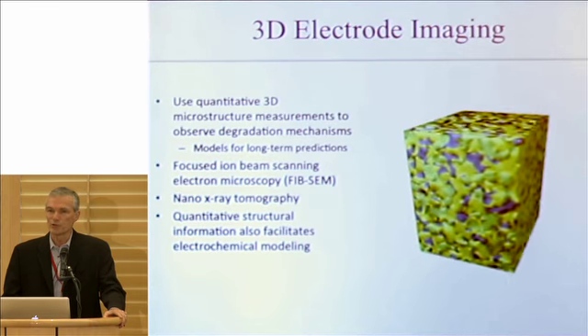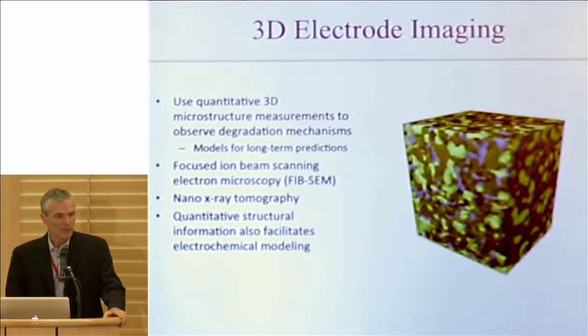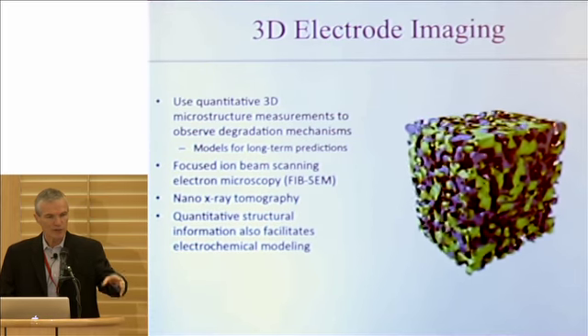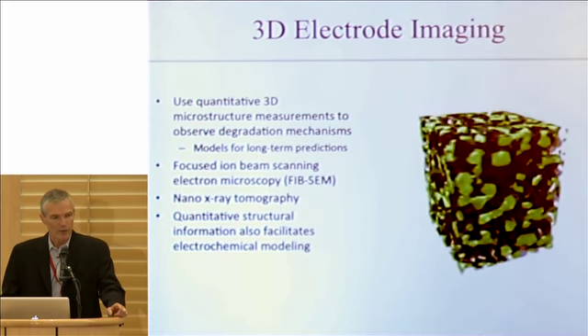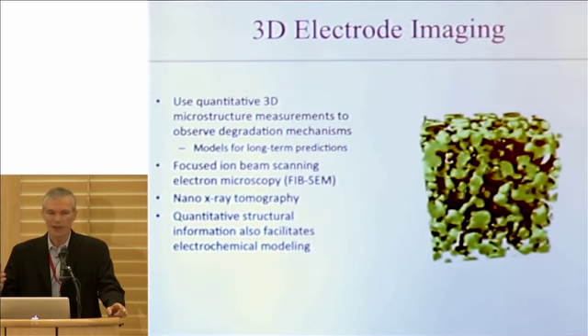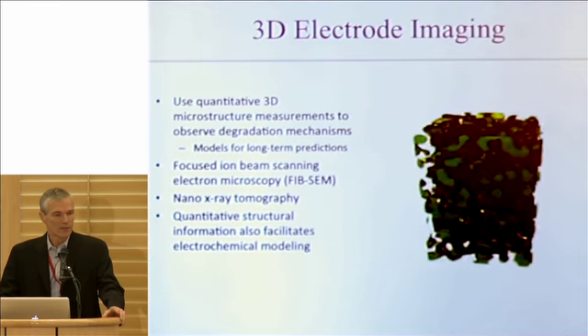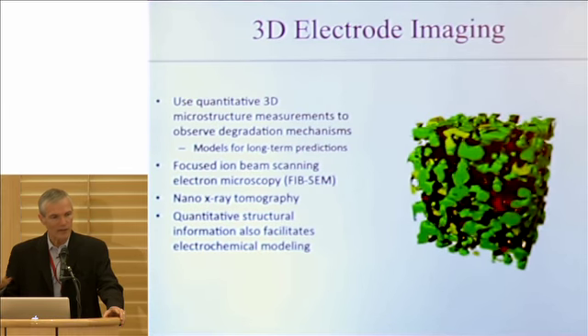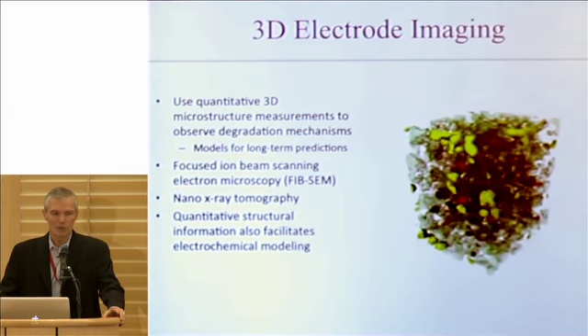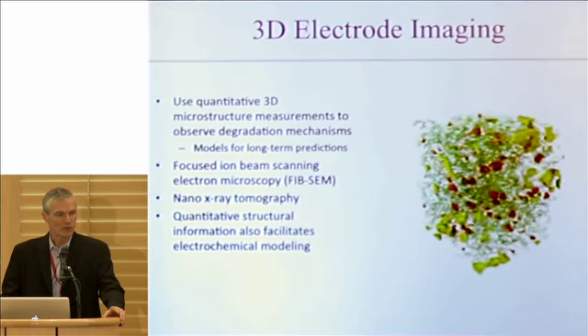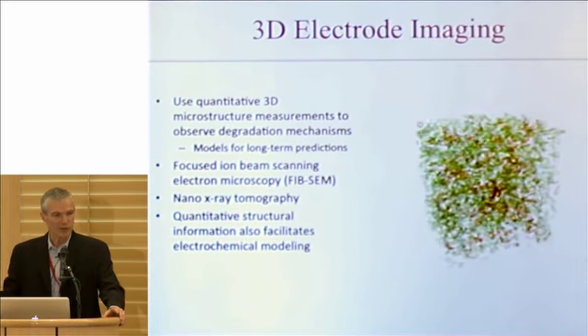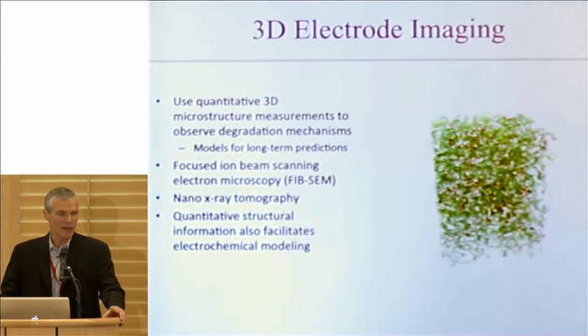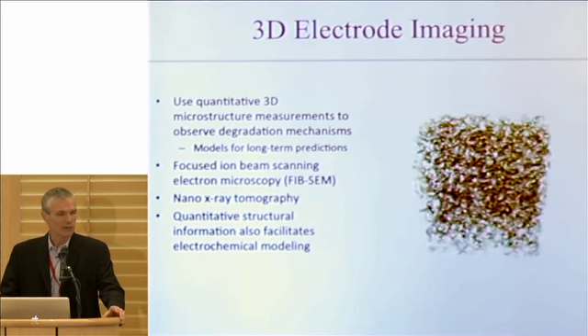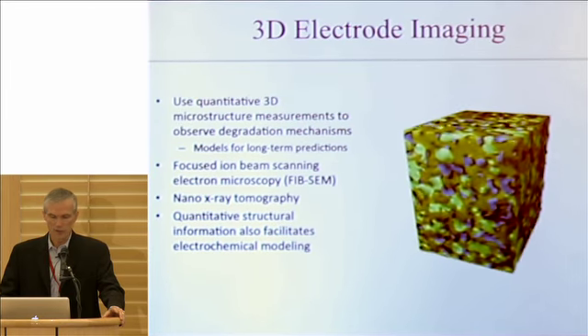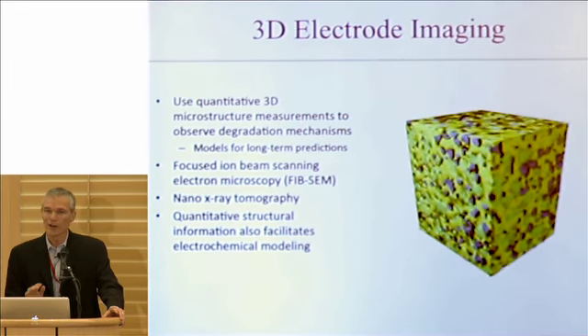One of the tools we're using is three-dimensional imaging of the electrode microstructure. This is showing some examples of a typical electrode structure, which is a fairly complex multi-phase structure. This is just illustrating some different ways we can view that structure. We can look at particles, how they're connected within the structure. Those green lines you're seeing are three-phase boundaries, which are the active sites for electrochemistry in these electrodes. And we're using a variety of techniques for characterizing these.